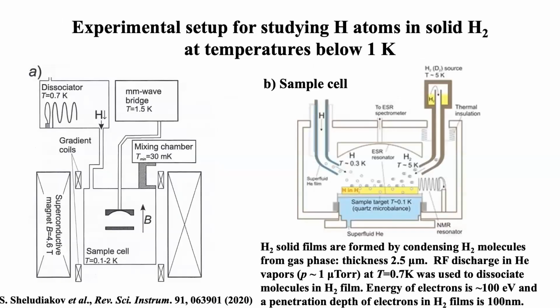I will start from our setup. Usually we use a setup based on a dilution refrigerator, which we use to cool down our sample. Our sample cell was placed in the center of the superconducting magnet, which can create a field of 4.6 Tesla. We use the ESR spectrometer, and this is the cavity, a Fabry-Perot cavity of the spectrometer.